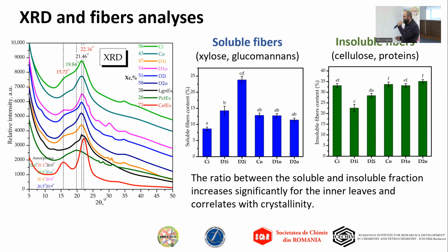Further, we correlate the diffraction spectra of all samples with the soluble fibers and insoluble fibers content, and the ratio between the soluble and insoluble fractions increased significantly for the inner leaves and correlates with the crystallinity. The crystallinity is correlated with a higher cellulose 1 alpha, respectively insoluble fibers.